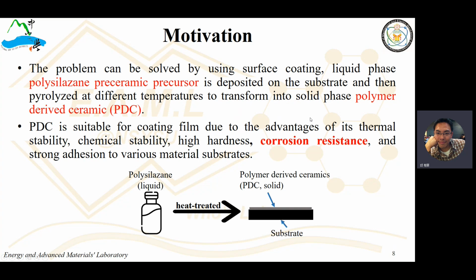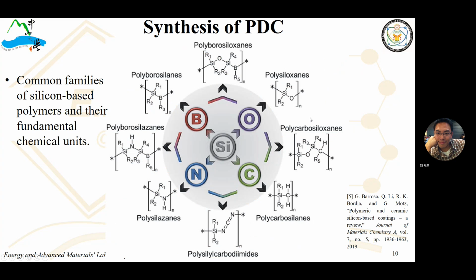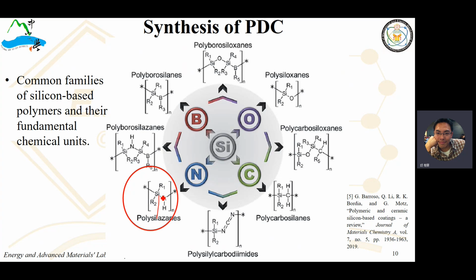Okay, and the material we're going to use is called PDC, which I already introduced a lot in a few previous special talks. The precursor is a polysilazane pre-ceramic precursor, and it can be easily deposited on different types of substrates. In this case, we're using what's called a polysilazane. That means this structure has the silicon-nitrogen bond right here. Silicon-nitrogen bond here.